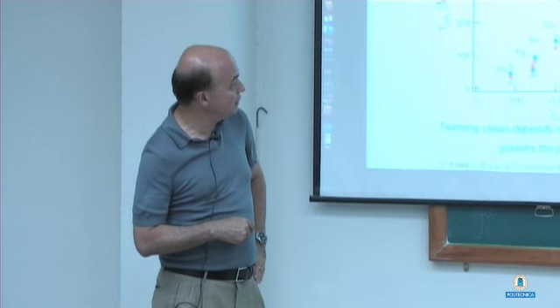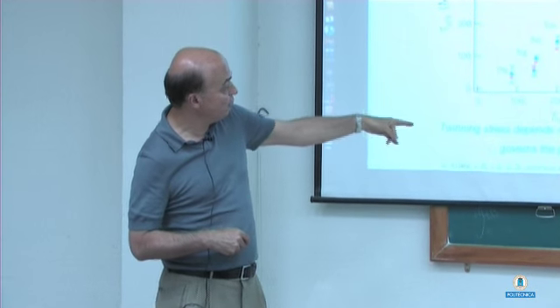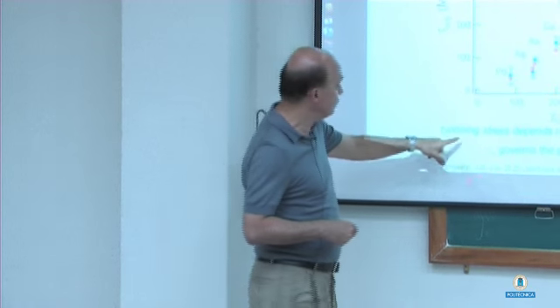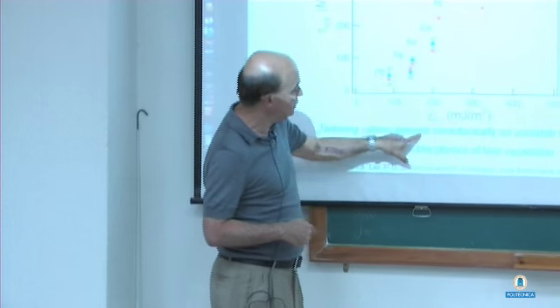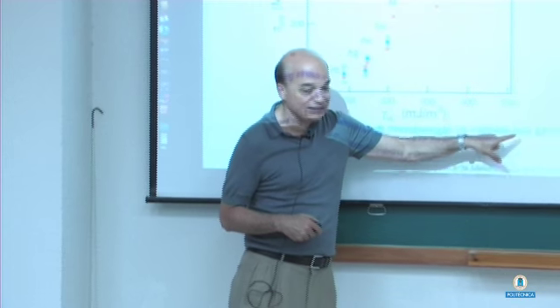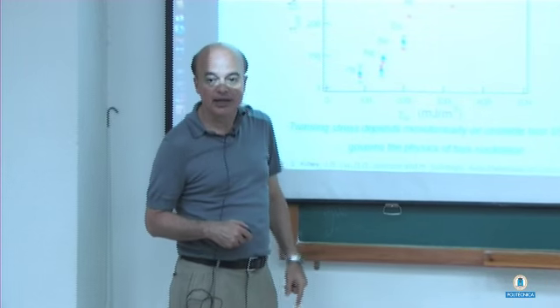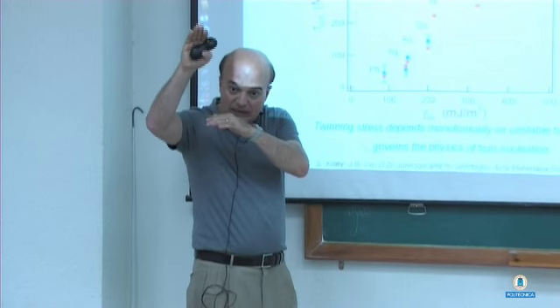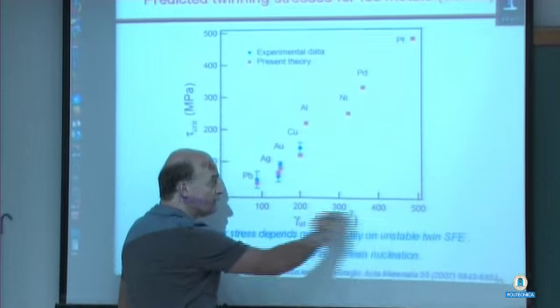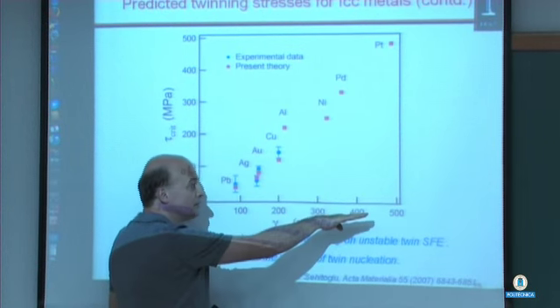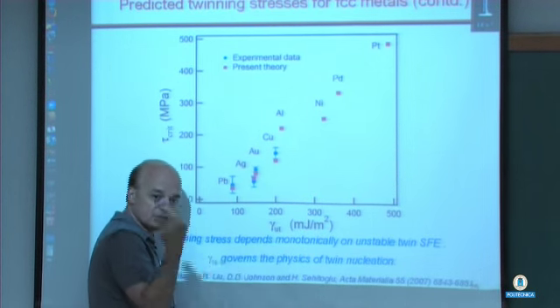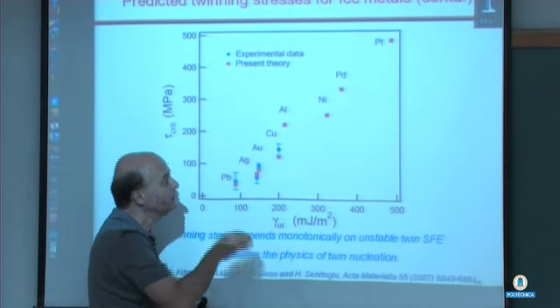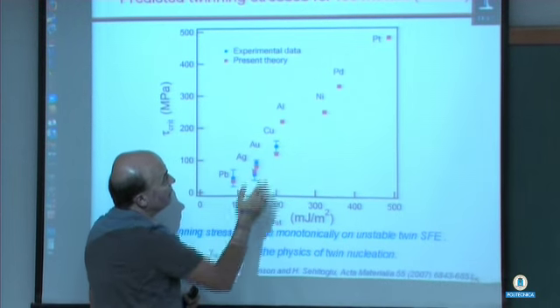Now, these are the entire results plotted versus gamma UT. What we're saying here is that twinning stress depends monotonically on unstable twin stacking fault energy, the gamma UT, that peak. There's a better correlation between critical stress and gamma UT. And the higher the gamma UT, the higher the twinning stress. Consistent with that equation, consistent with the experimental data here.